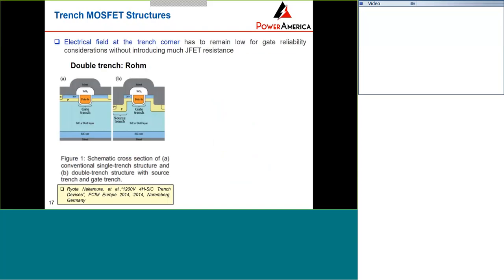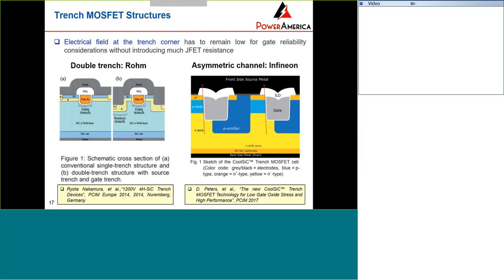The two major trench MOSFET structures are right now developed by different companies. The first structure is the double trench from ROHM. You can see that there are very deep P-type implantations around the poly gate to protect the high electric field from the drain bias. Infineon uses an asymmetric channel to protect the corner. Both structures look different, but the physics is pretty much the same. Both of them use deep implants to shield the field from the drain bias, so they could effectively reduce the field in the oxide corner.